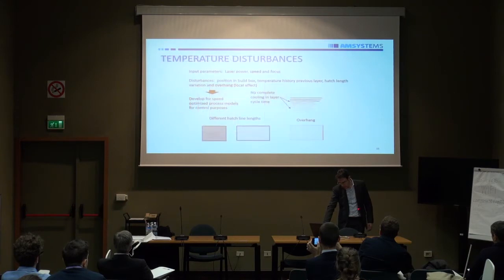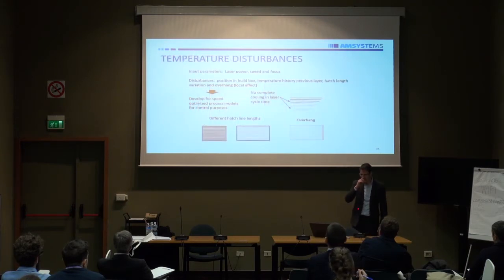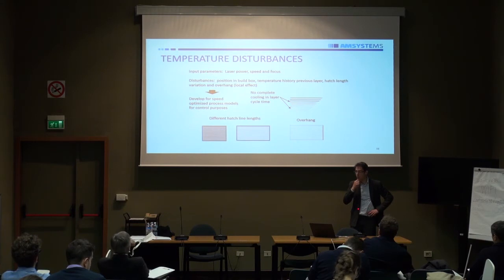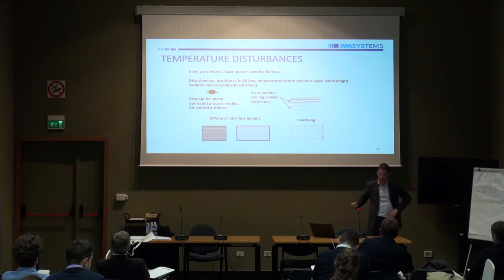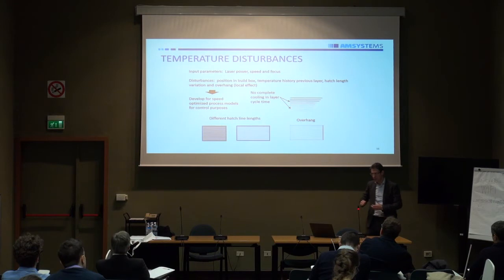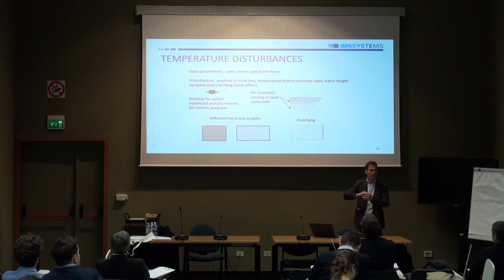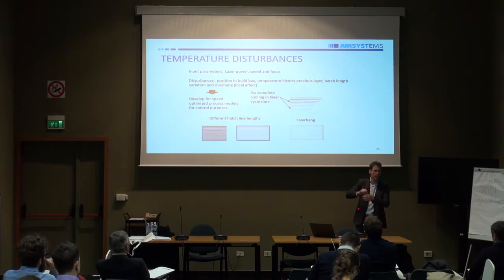So I will show you, because we did quite some modeling in this field, and especially we started with metal, because we started with a lot of metal projects. And what we saw there is that, for example, this laser power you can control. But what you cannot control, or maybe you can control, is that during your build, your product heats up. It doesn't have time to cool down. And then also, not intended, your material becomes hotter, and your melt pool is different than when you just started.